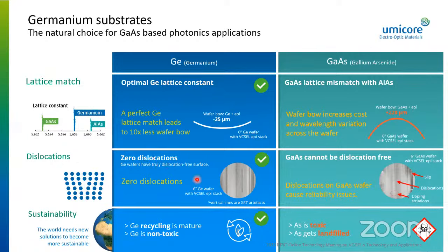And because of that, the wafer making process is very similar to silicon. And in fact, you can make it dislocation free. So every germanium wafer that we sell is dislocation free. So it's true zero EPD. You have none of them. With gallium arsenide, there are also ways to significantly decrease the number of dislocations, if not to get rid of them completely. But that, of course, first of all, increases price. And second of all, you still have some dislocations left there.